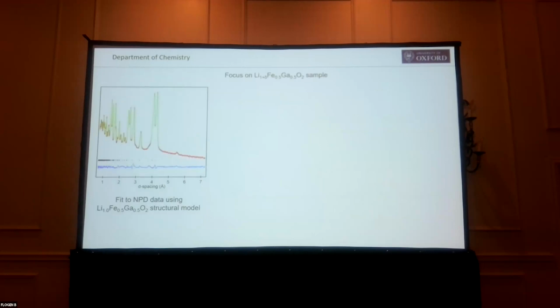And again, if we take neutron diffraction data, we can get a nice fit to the data. But actually, this model doesn't contain any extra lithium. So we know chemically we've got the extra lithium in there, so finding the lithium is actually a bit of a challenge. Lithium is quite a weak scatterer of neutrons, but it has one useful feature there: it's negative.